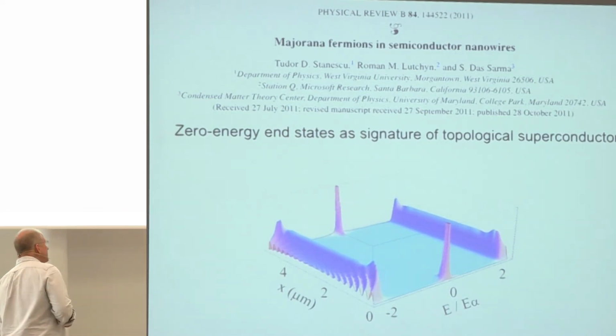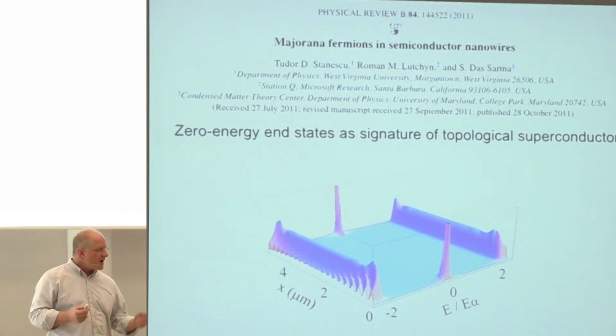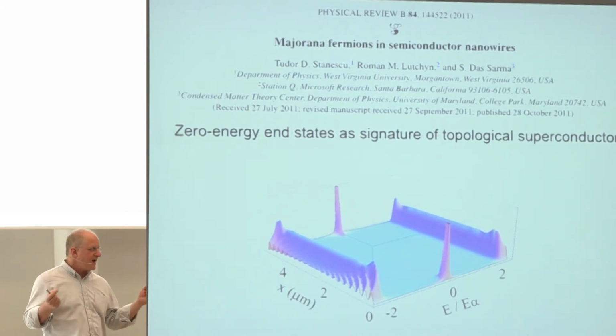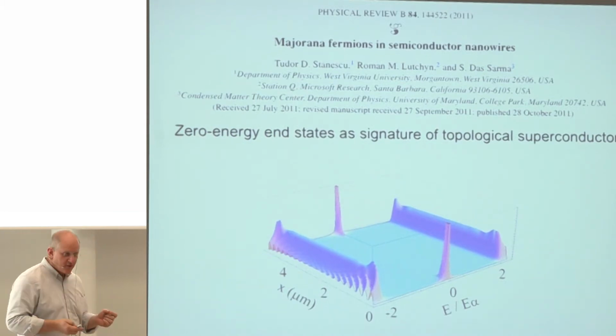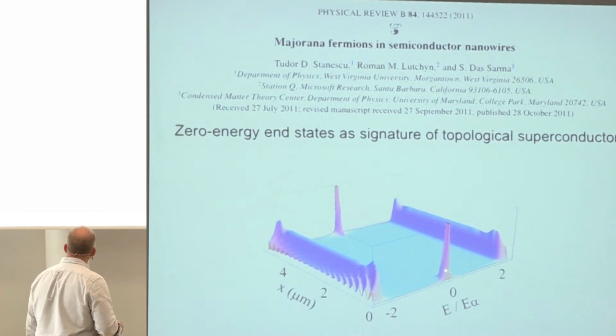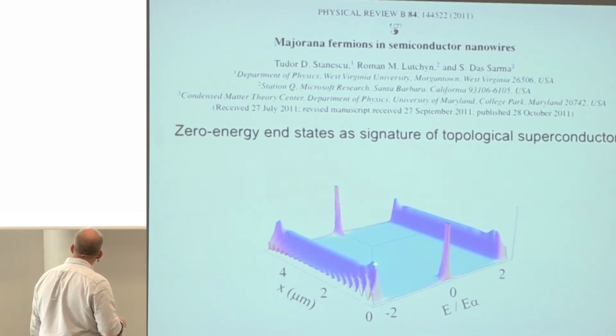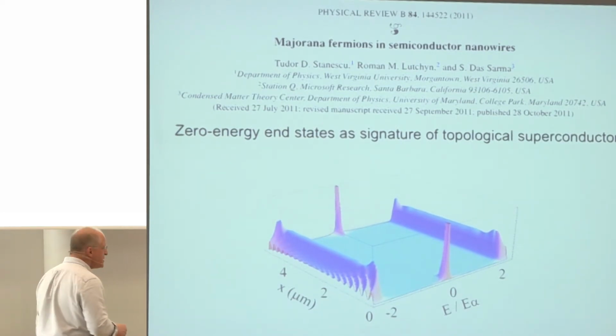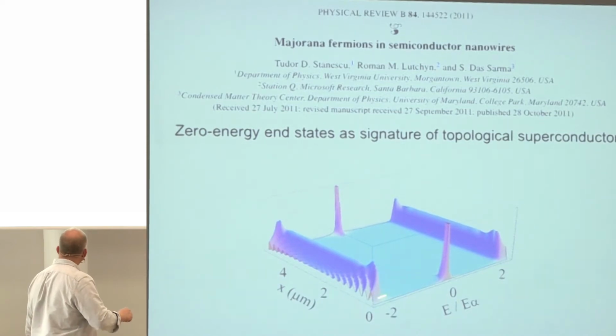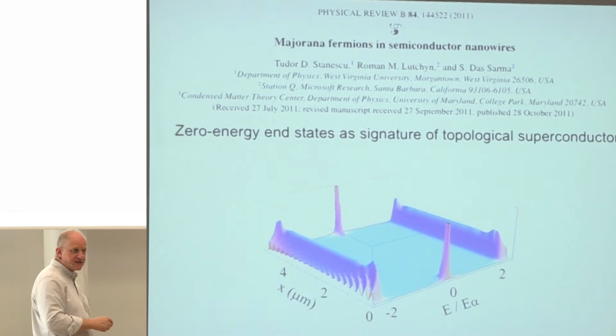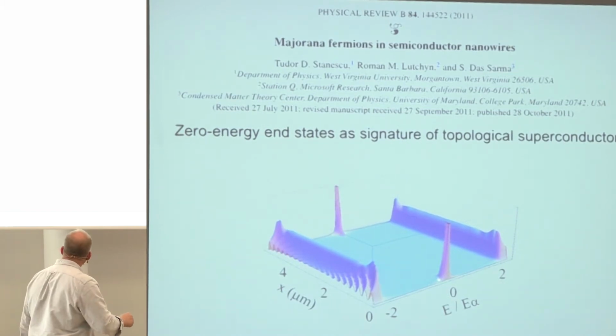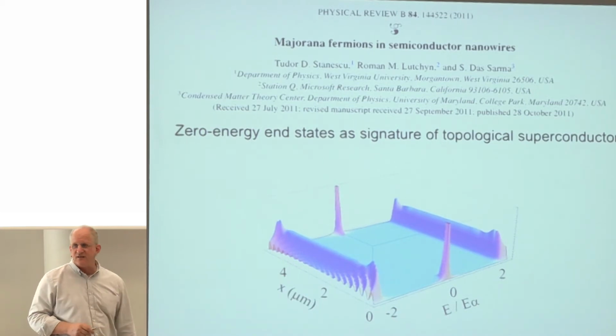And so we have been instructed that the presence of a Majorana fermion, as these things are called, or a Majorana end state, gives a very particular signature. Here X is a spatial dimension, so this is one end and this is the other end of a finite topological superconductor that supports those Majorana states at their ends. Measuring the density of states, you can see, if you're familiar with superconductors, a traditional so-called BCS or superconducting density of states, and nothing below the gap. This whole area in energy below the superconducting gap has no density of states at all, like a regular superconductor, except, unlike a regular superconductor, it does have a strong density of states at its ends.